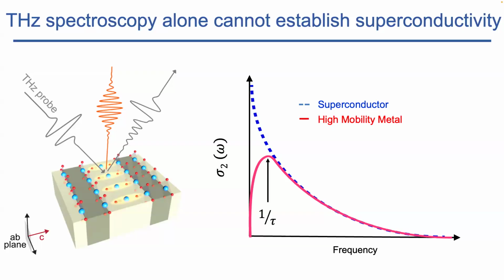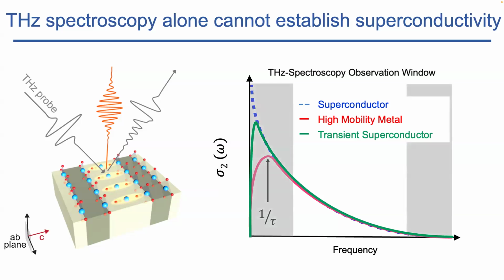But now let's take a superconductor that only lives for a timescale tau, and let's plot sigma 2. The transient superconductor kind of looks like a Drude metal, where the lifetime of the superconductor goes into the equations for the scattering. Furthermore, if you're measuring only over this region, we can discuss whether it is reasonable to imagine that the scattering rate of a metal can be so low. But it becomes a little bit of a subjective statement where you say, well, this thing looks like 1 over omega just because I'm measuring in the same range where accelerated quasiparticles might also look like 1 over omega. Now, for full disclosure, this 1 over tau would have to be extraordinarily small. But then again, who knows, right? It's a driven phase and maybe it's coherent, or maybe you have, anyways.